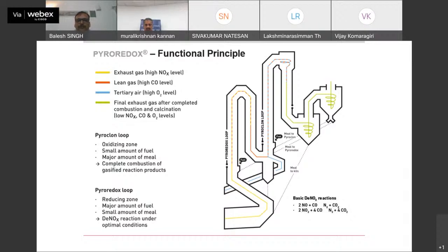So this is the alternate where there will be no OPEX cost like ammonia spray, and there will be no hazard in handling chemicals. This is a loop additional to the calciner, where a NOx reduction technology is maintained. That means, if we see the loop, the NOx coming from the kiln inlet goes into the pyro redox loop, where we maintain a reducing atmosphere, that means lack of oxygen in that area. Definitely there will be some CO percentage, but this will reduce the NOx